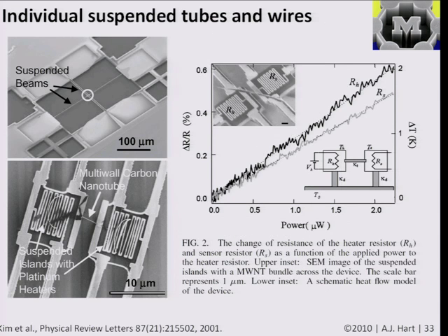And there have been a lot of very clever measurements on measuring things like individual nanowires or carbon nanotubes and fibers and so on. And the basic idea is something like this, where you microfabricate this very complex structure where you have a suspended bridge. So these are really fine insulating material. And then if you zoom in on this part, you see a long platinum wire here and another long platinum wire all coiled up on the other side.